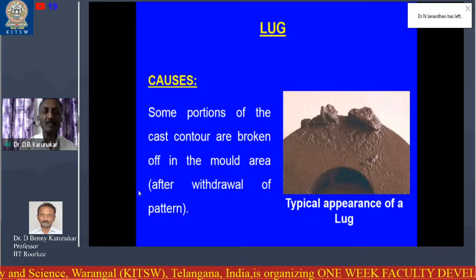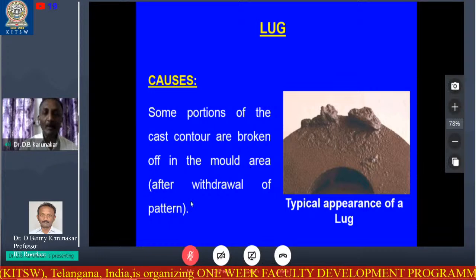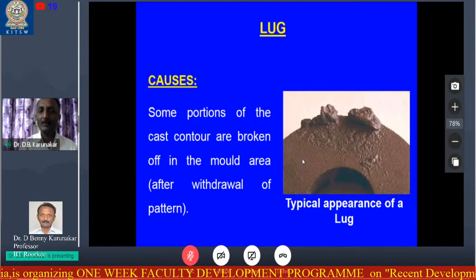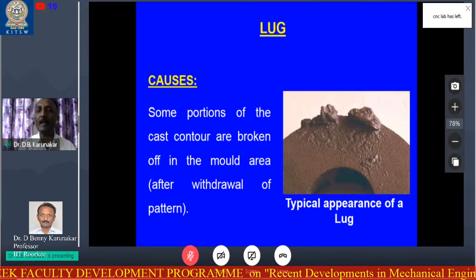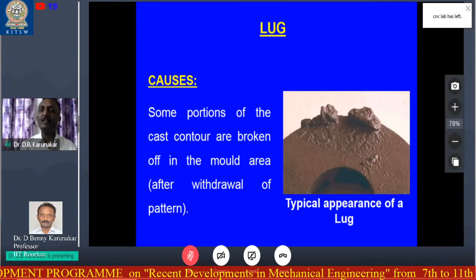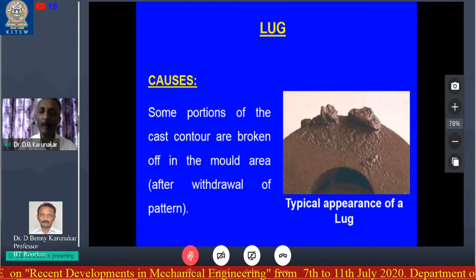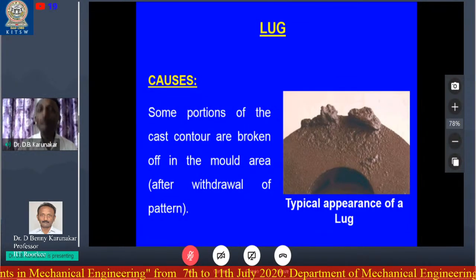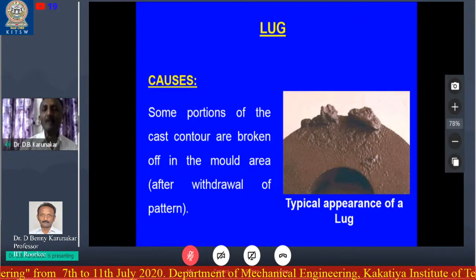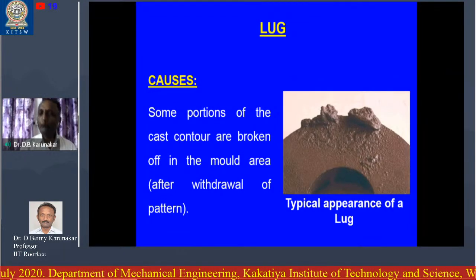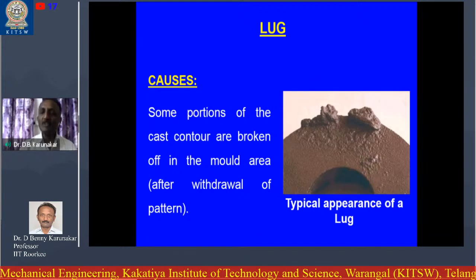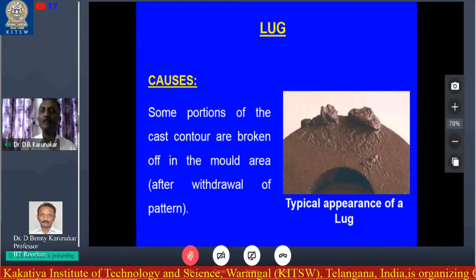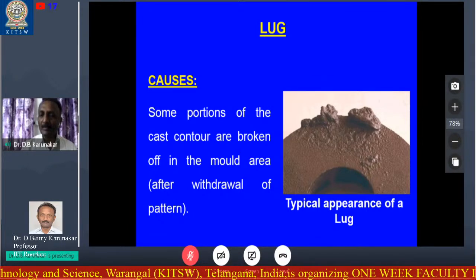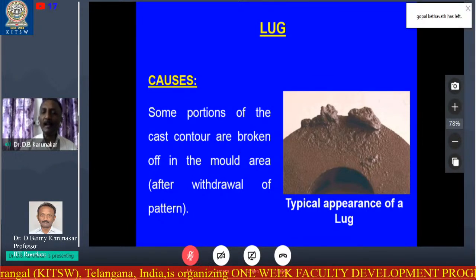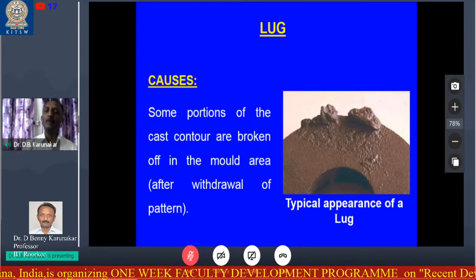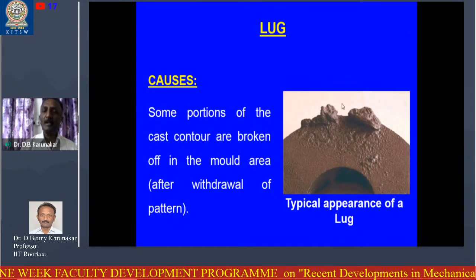Some portion of the cast contour is broken off in the mold area after withdrawal of the pattern. In the previous case, molten metal penetrated between larger sand grains and formed an unwanted deposit, but this is not that case. Here, somewhere inside the molding cavity, some portion is damaged or broken. Because of that damage, molten metal goes and solidifies in an unwanted portion, and that is how this unwanted projection arises.